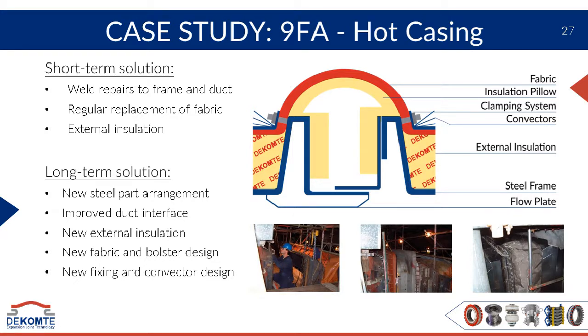In that case study, we show a W frame system which was installed. So we cut out the existing flanges of the duct as well, because we realise in this case that the adjacent flanges of the duct and the adjacent stiffeners on the duct are also exacerbating that issue of stress raising by the thermal gradient. So we've looked to really integrate the frame to the duct, and we've changed the stiffening system on the duct in order that the expansion joint frame is effectively the stiffener, and that's managing that temperature profile and reducing that stress in its own frame to allow for the maximum number of cycles. The whole system was supplied and installed by DEKOMTE. And we also improved the adjacent duct insulation and obviously replaced all the soft goods inside the expansion joint scope.